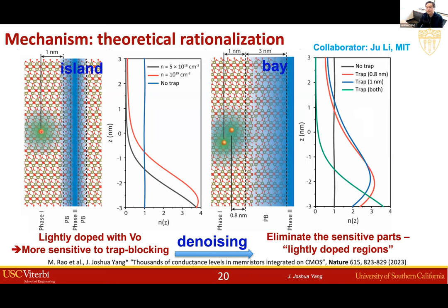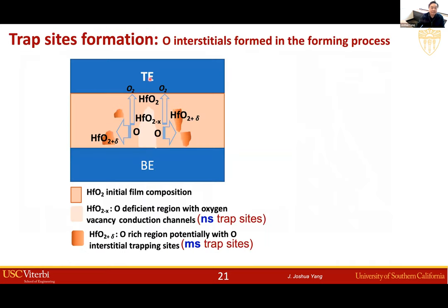So in this case, the trap centers are oxygen interstitials. And how can you get oxygen interstitial in an oxide like hafnium oxide? So the as prepared film is stoichiometric hafnium dioxide. And how can you get some HfO2+δ, extra oxygen, near the channel? So it is easy to understand. In fact, the device always needs an electrical forming process, which is a process where you apply electrical field to quickly remove some oxygen from the dioxide and get oxygen vacancies in the channel.